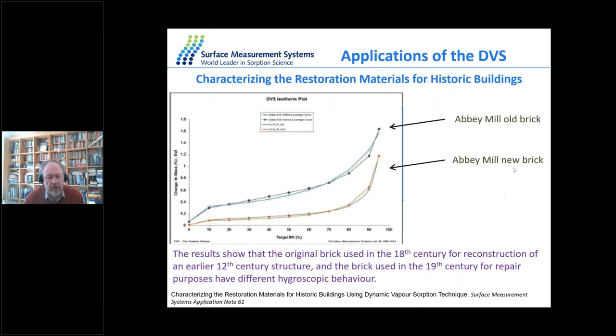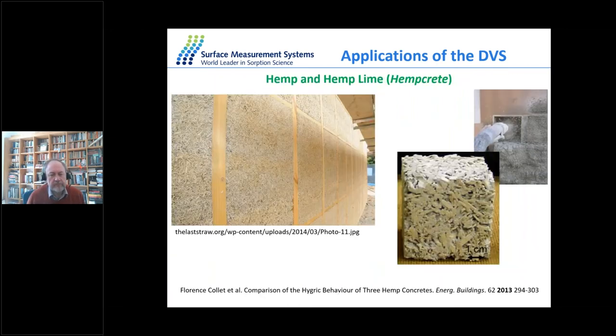So here you can see the isotherms. The bricks used in the 18th century reconstruction, which is part of a 12th century structure, and the brick used in the 19th century for repair, have quite different water absorbing behaviors. And you need to keep an eye on that. That might have some implications if you are putting those bricks together. But again, even for materials that have low uptake, the DVS technique can be quite sensitive.